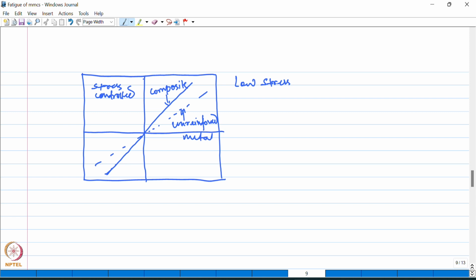So here you can see that at a given cyclic stress, that is delta sigma composite is equal to delta sigma metal, the total strain in the composite is lower, that is delta epsilon composite is lower than delta epsilon metal. Okay, so here this delta epsilon is basically the total strain. Okay, this is true at high stress also.